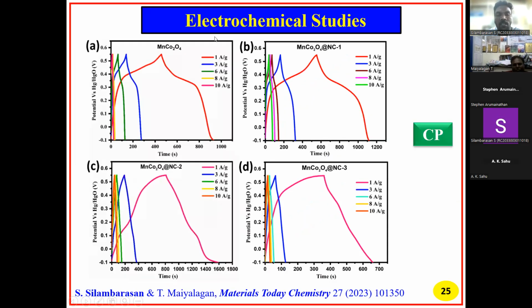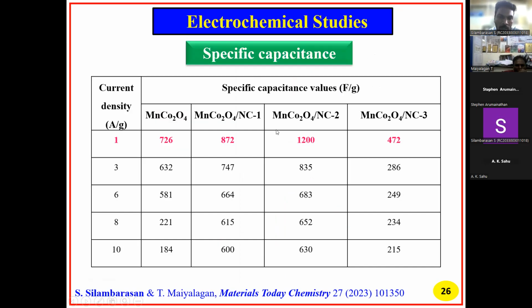Next, the charge and discharge. Here, the applied current density is around 1 ampere per gram up to 10 ampere per gram. Overall, compared to MnCo2O4, sample 1 and sample 3, sample 2 has more discharging time and more specific capacitance. Moving to the next slide, we show the specific capacitance table. At a current density of 1 amp per gram, compared to bare, sample 1 and sample 3, sample 2 has the higher specific capacitance, with good conductivity, around 1200 farad per gram.